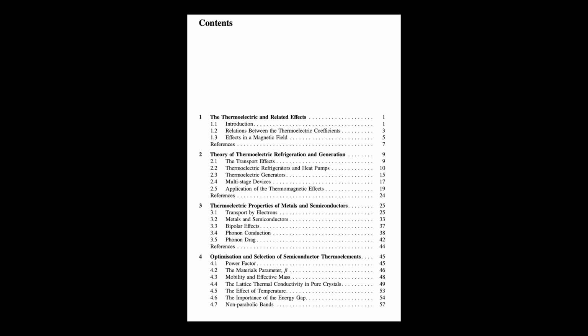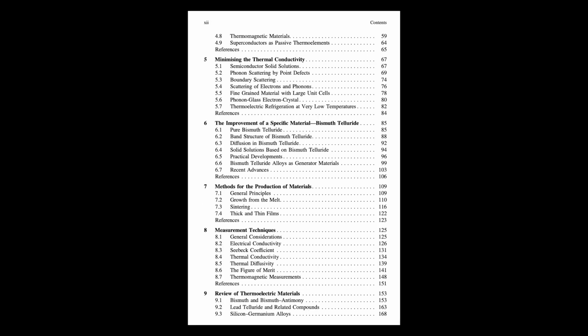And Ettingshausen? That's kind of the reverse. You run a current through the material, apply a perpendicular magnetic field, and you can create a temperature difference across the material, again, perpendicular to both current and field. Just like Seebeck and Peltier are linked, Nernst and Ettingshausen are also related through another thermodynamic relation.